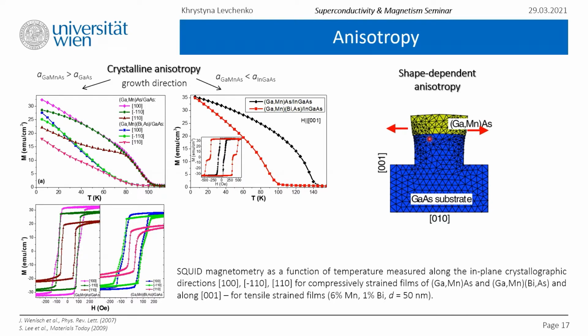Actually, the best gallium manganese arsenide layers showed TC around 200 for the bulk materials and 210 for the 2D structures. Despite this, I would still call it a success because this material has a history of improvements of its TC. It already overcame once in its history the limitations by lowering the growth temperature. Perhaps in the future, new improvements will be introduced and we will have the same high quality material, but with even higher TC. For now, I would like to say that we observe a relatively high TC for magnetic spin ordering, well below the Curie temperature in all the investigated layers.